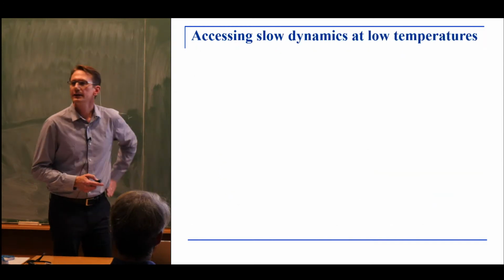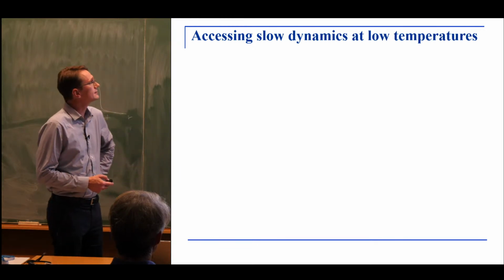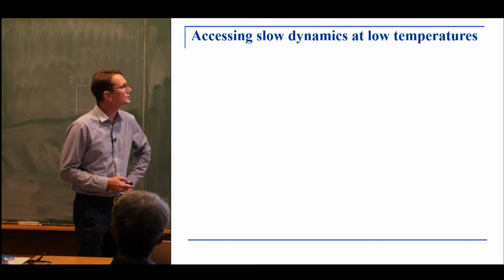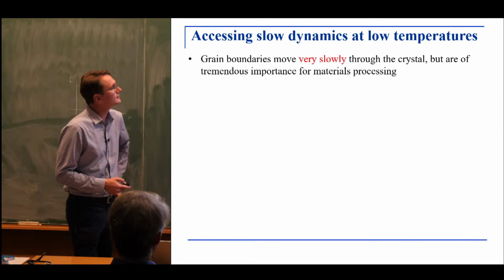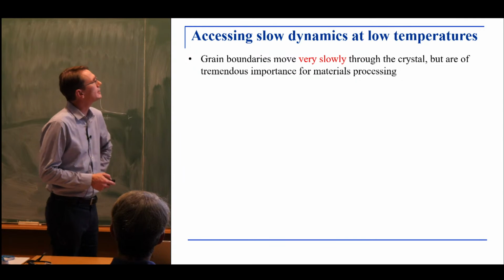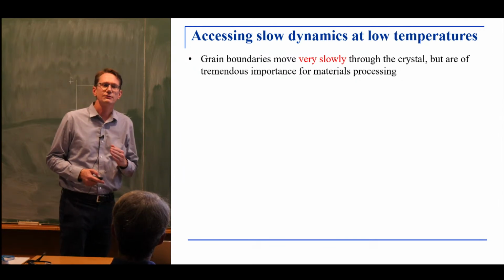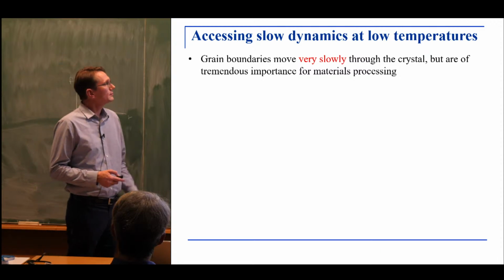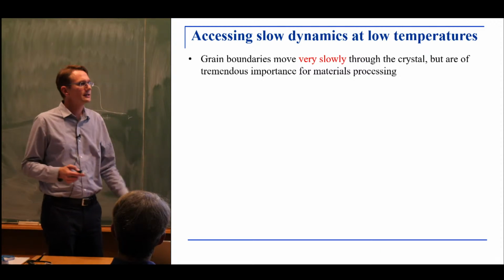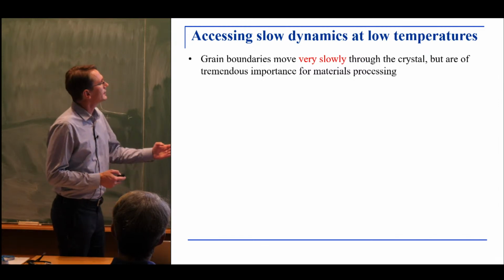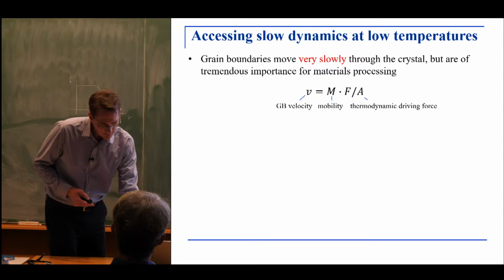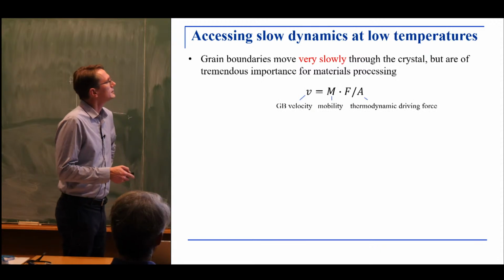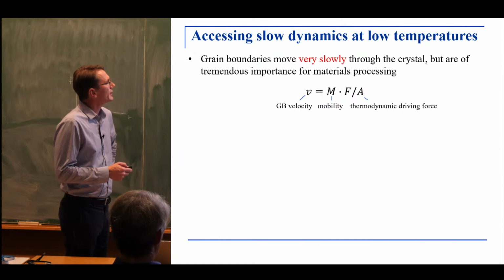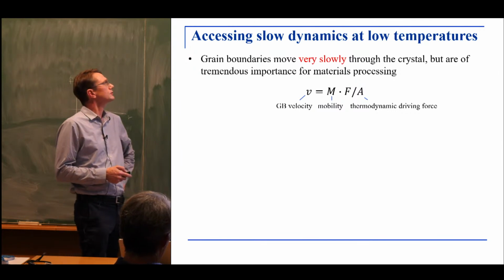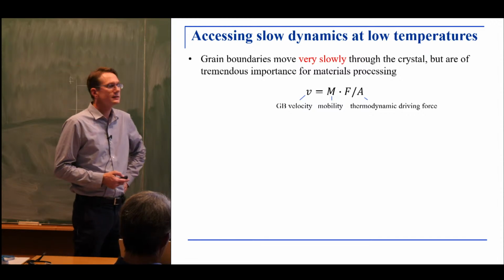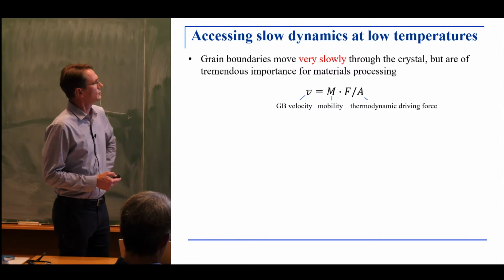A related problem that we face in material simulations is accessing slow dynamics in general, in particular at long time scales. This arises, for instance, in the mobility of grain boundaries, which is a very important phenomenon in materials processing. But grain boundaries are extended defects, they're interfaces, and they move very, very slowly. Studying that with molecular simulations is therefore a great challenge. One would usually describe grain boundaries by a coefficient called the mobility, which is the proportionality coefficient between grain boundary velocity and the thermodynamic driving force, or the driving pressure, if you want.